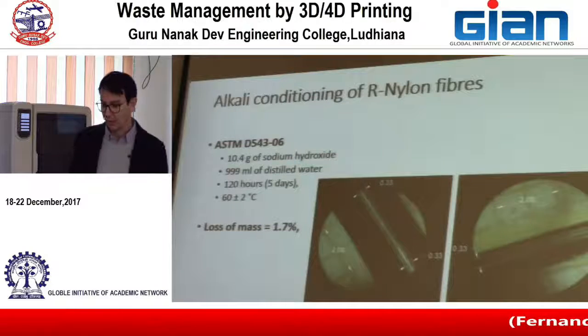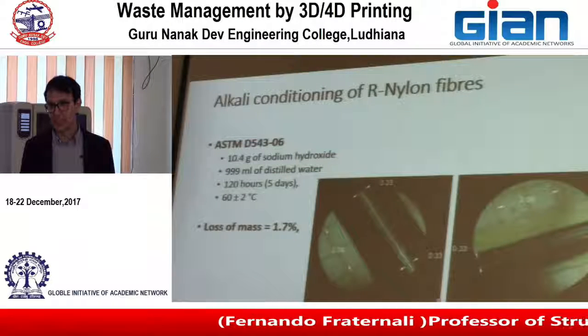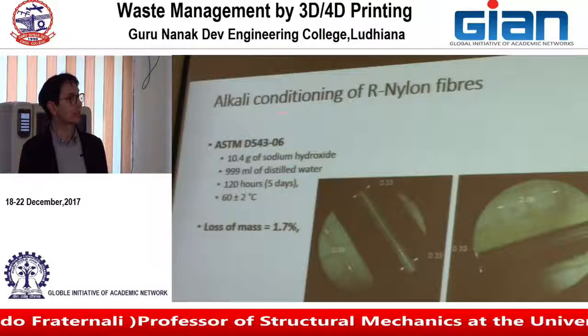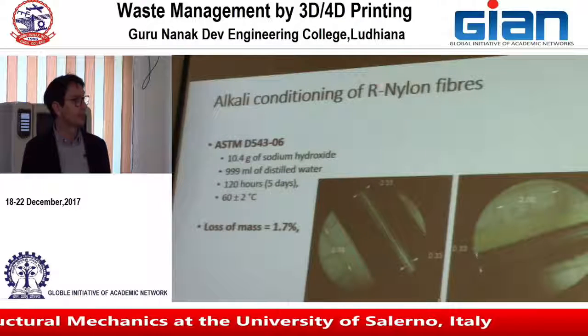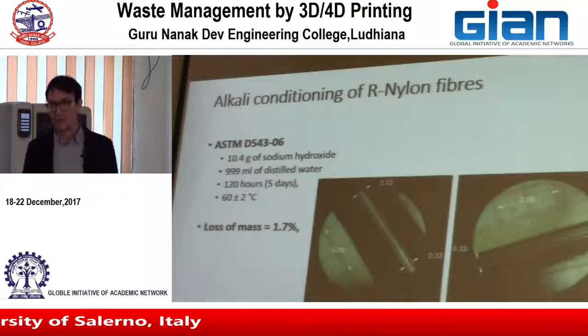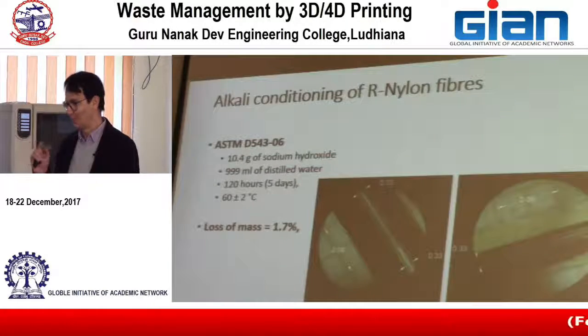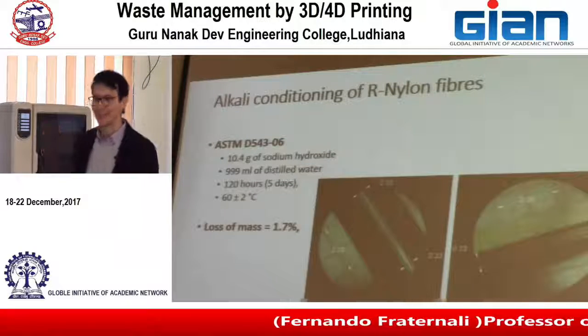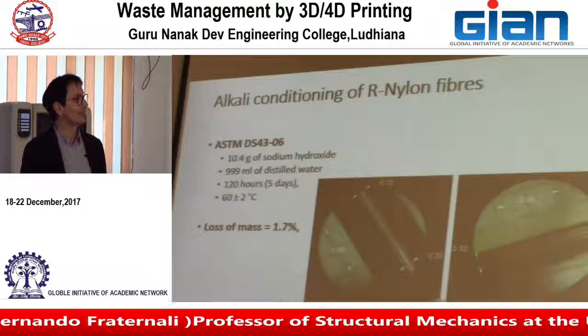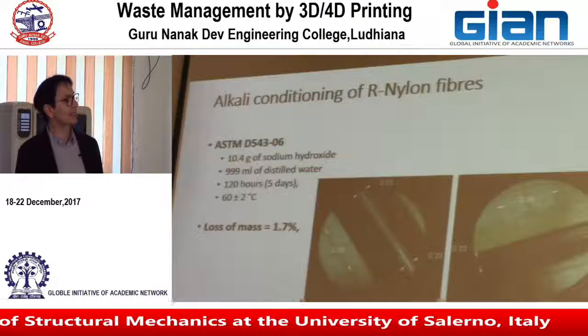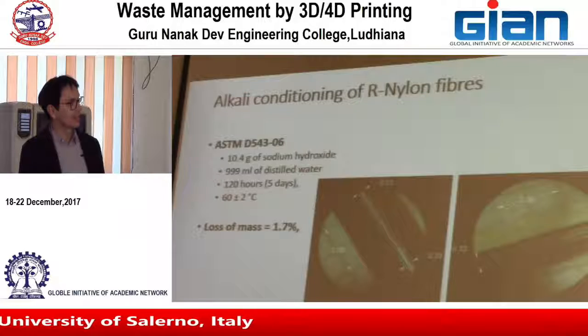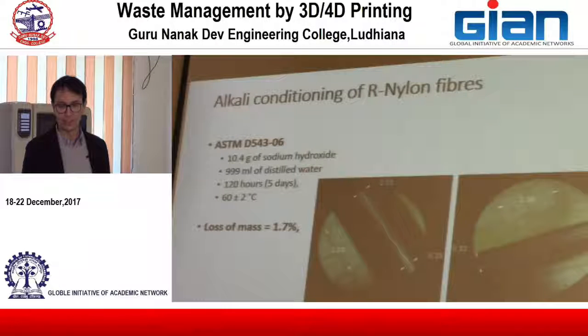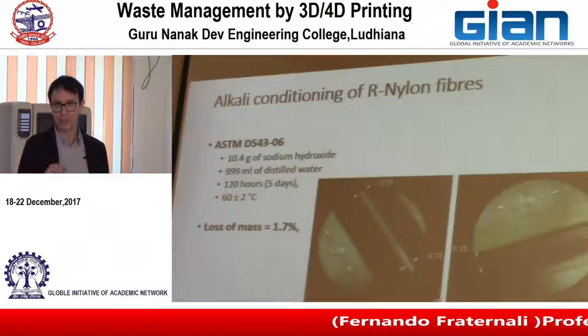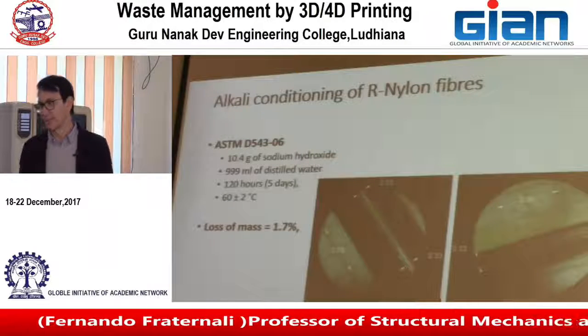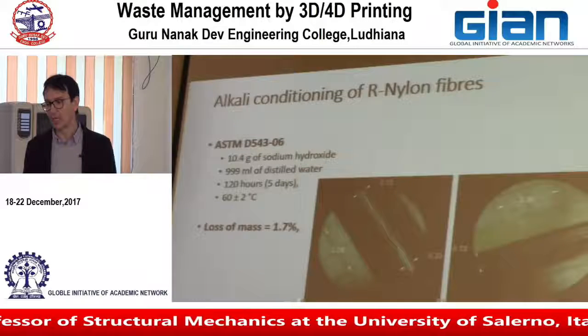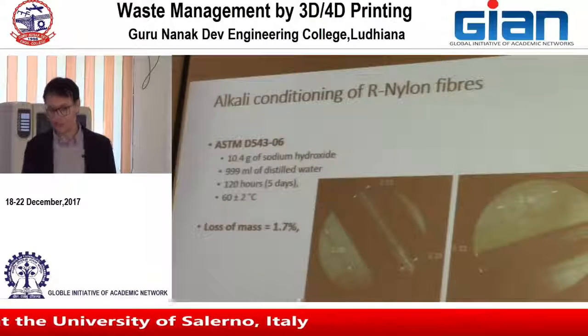In terms of durability, we carried out alkali conditioning of nylon fibers, and the fibers were obtained by manual cutting of the fishing nets, manual cutting. And we conducted alkali conditioning tests by basically immersing the fibers in an alkali solution, and then we measured the mechanical properties before and after the immersion in the alkali solution in order to measure the durability of the material.